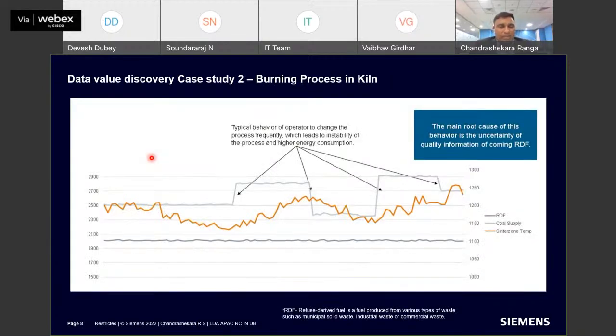And how does it look when you are using alternative fuel? Every cement industry wants to move away from fossil fuels, like the coal they are burning, and use alternative fuels. But using alternative fuels results in a lot of fluctuation. You can see here RDF, coal supply, and sintering zone temperature. The sintering zone temperature ranges around 1100 to 1250 degrees. When the RDF is introduced, it's predominantly unstable, and the calorific values vary a little bit here and there. But more important to notice is the operator behavior, right?